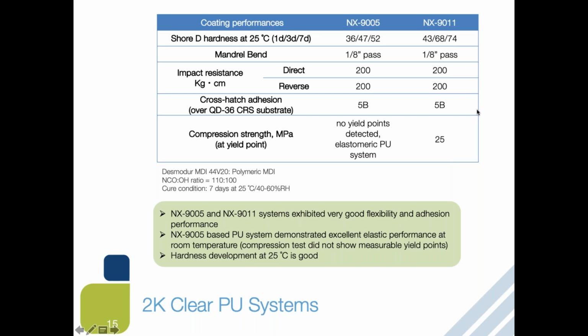And when we measured the compression strength of this system, since it is a flooring application, especially in 9005, we observed elastomeric performance when we were trying to measure the yield point, the compression yield point. There's no detectable point, which typically indicates that the system is very elastomeric.